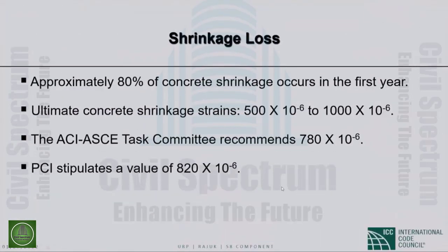Shrinkage loss. It has been shown that approximately 80% of shrinkage occurs in the first year. Shrinkage means that with time, it's a property of concrete. We cannot avoid it. It will shrink. Some concrete will shrink more, some concrete will shrink less. It depends on water cement ratio and other factors, humidity and temperature, environmental conditions. Now, there's nothing wrong with shrinkage, but if you restrain that member, the concrete is not allowed to shrink. As a result, you may end up with shrinkage cracks. In the USA, we see all the time, in bridge decks, even new decks, they have these transverse cracks. So cracking is nothing wrong as long as we manage it. And as you know, that's why we provide shrinkage and temperature steel in slabs and decks.